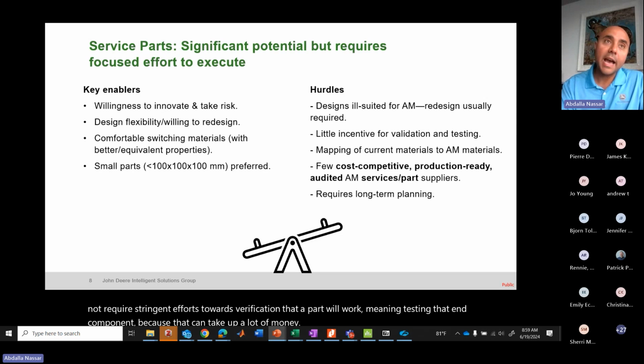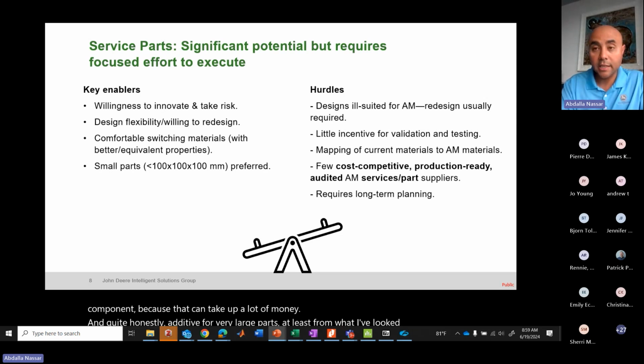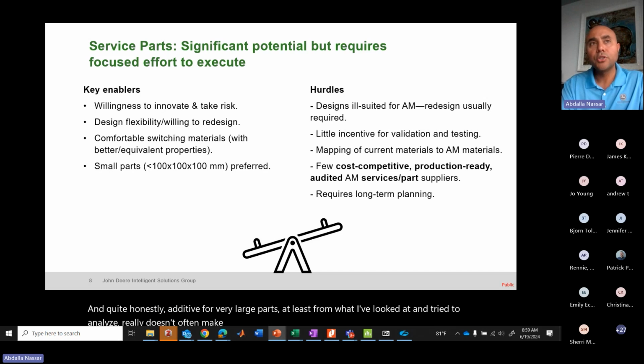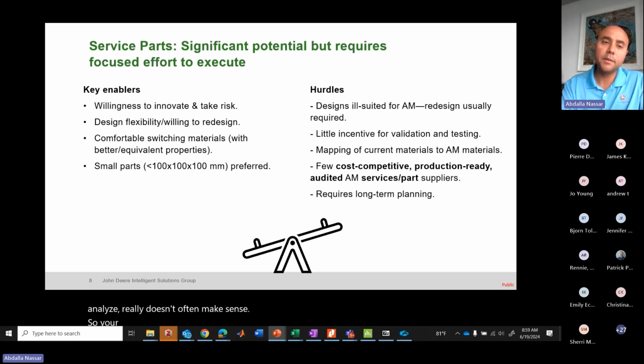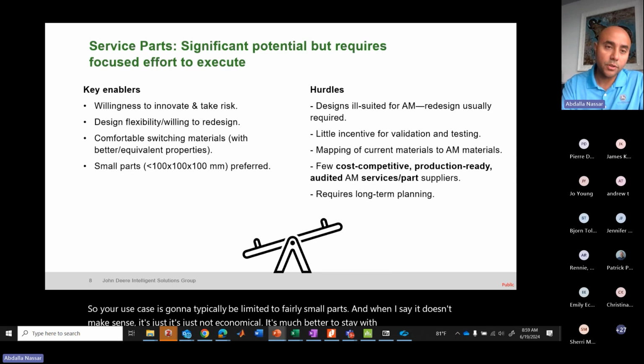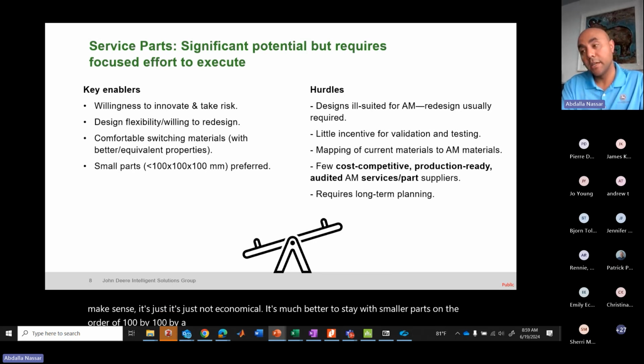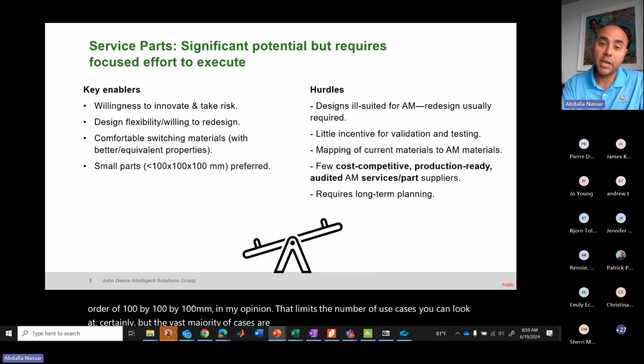And quite honestly, additive for very large parts, at least from what I've looked at and tried to analyze, really doesn't often make sense. So your use case is going to typically be limited to fairly small parts. And when I say it doesn't make sense, it's just not economical. It's much better to stay with smaller parts on the order of 100 by 100 by 100 millimeter, in my opinion. That limits the number of use cases you can look at, certainly, but the vast majority of cases are going to be in those smaller size parts today. We'll see as the technology evolves.